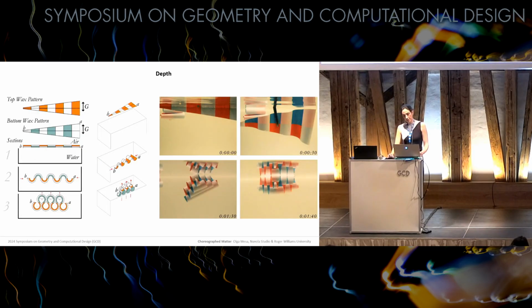And now in the depth setting, the movements occur underwater. This enables the possibility of seeing transformations from both sides of the designs. By applying wax on the front and the back side of the paper in an alternating pattern and accounting for the direction of the grain, the flat origami displays rolling and sinuous configurations when in contact with water.